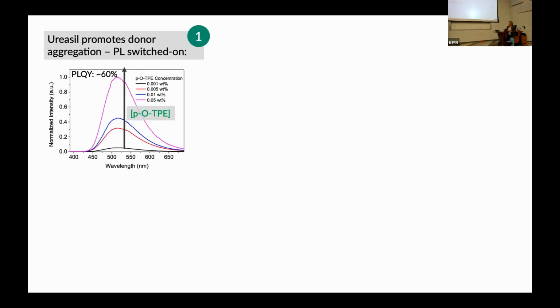So what we wanted to see, first of all, was, did the ureasil switch on the luminescence from the donor? Does it cause aggregation-induced emission? And that's exactly what we see. As we increase the concentration of our donor, we get an increase in the emission intensity as the polymer chains are packed closer together, and we increase the emission. And so we get a maximum quantum yield of around 60%, which is not brilliant, but it's acceptable in this case.